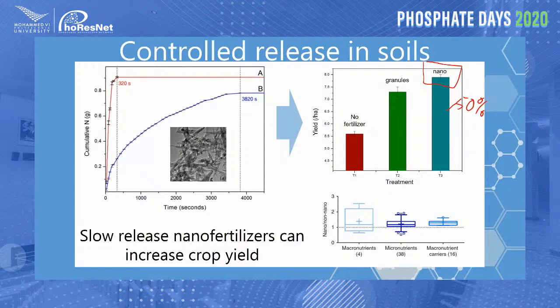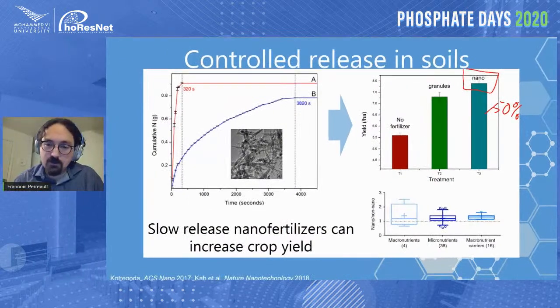So here on the bottom right, there's a very important study that was published recently in Nature Nanotechnology, where they look at essentially a meta-analysis of all the controlled release devices that were done for agricultural fertilizer. And what they found is that when you look at the nano to non-nano ratio, a value more than 1 indicates an improvement compared to the non-nano form. You can see that all different types of nanofertilizer perform better than the non-nano form for all types of macronutrients. But most specifically, when you look at macronutrients fertilizer, this is really where all the opportunity lies, and the most promising opportunities can be achieved.